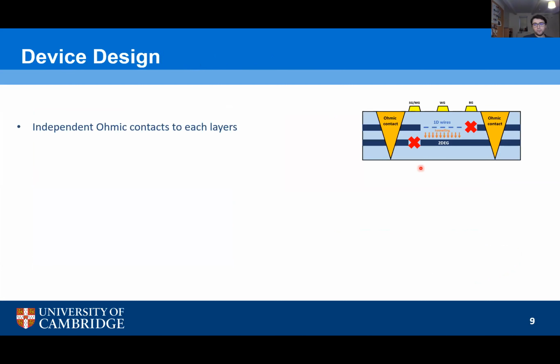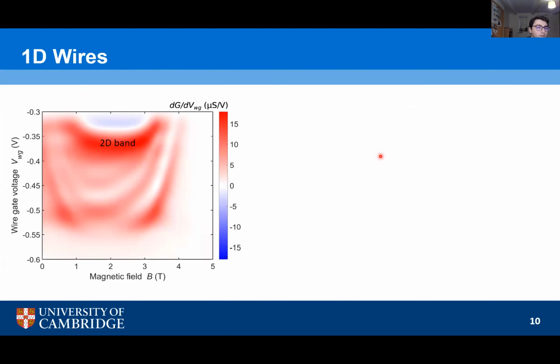Anyway, the important thing to know is that we have two 2D systems in close proximity, and we have independent contact to each. So by appropriately biasing the gates, we can make sure that any current measured between source and drain has to result from tunneling, and then we laterally squeeze the top well alone into an array of 1D wires, and we can compare that to a well understood 2D system. So this is what our wires look like.